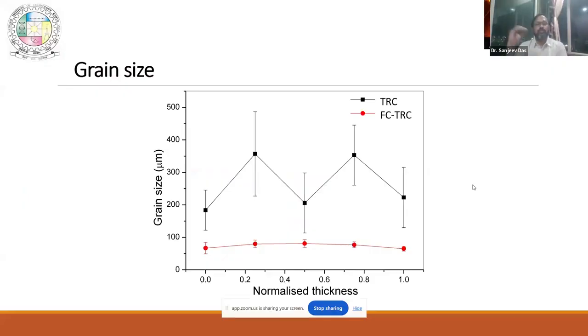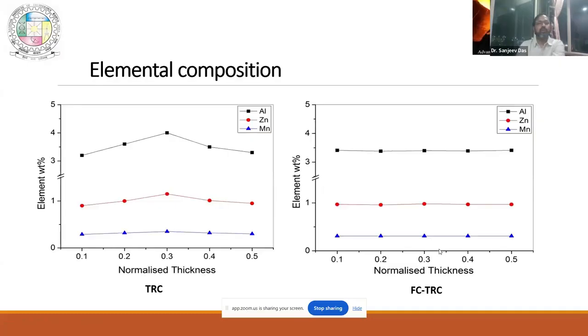Now here you can see the grain size distribution, the previous picture. You will see TRC is the black one. You will see that the grains are increasing, decreasing, and a lot of randomness is there. Even the standard deviation is very high. But if you see the forced convection one, it is quite uniform from one surface to another surface. So we can achieve a uniform grain structure.